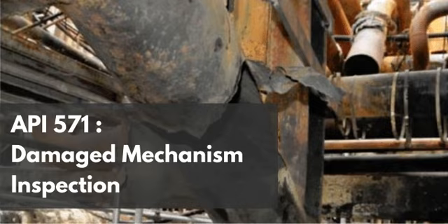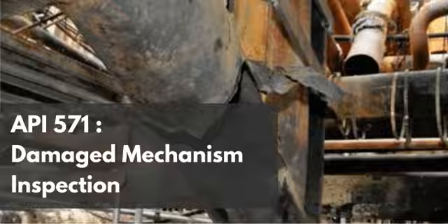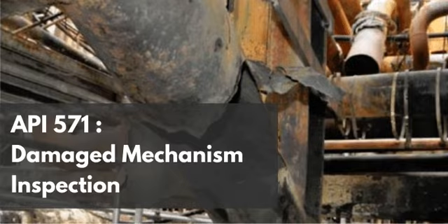Imagine a massive 36-inch diameter lean amine line. It was fabricated in a shop, fully heat-treated in a massive furnace, and it is entirely immune to Amine SCC. Okay, totally safe. But then, 5 years later, a contractor needs to run a small half-inch electrical conduit next to it. They use a standard arc welder to attach a tiny 2-inch steel bracket directly onto the outside of the 36-inch amine pipe to support the conduit. It's a tiny weld. It barely penetrates the surface. Why is it so dangerous?